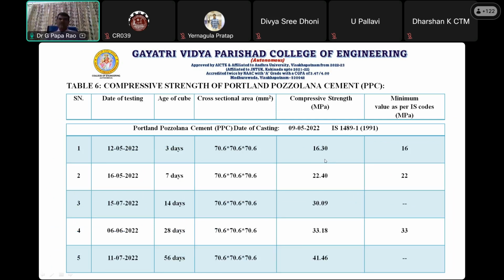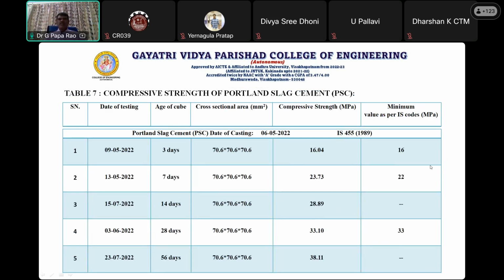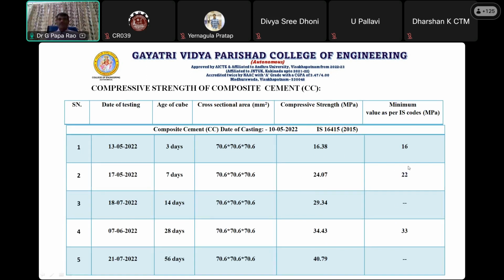Similarly for PPC, the requirement is 16 MPa at 3 days, 22 at 7 days, and 33. These are our laboratory tests: we got 16.3, 22.4 and 33.18. Therefore, we can proceed further with our PPC for further tests. Similarly, Portland slag cement, PSC, we have tested up to 56 and 90 days also, because of the durability tests. Here again, PSC got 16.04, 23.73 and 33. So these values meet our Indian standard specifications.